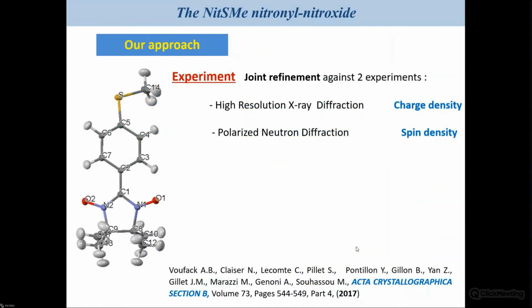So our idea was to combine X-ray diffraction and polarized neutron diffraction experiments together in a joint refinement to have a more precise distribution of the spin density in the system, and also to compare that to very precise theoretical calculations. Those theoretical calculations are DFT calculations and CASSCF calculations.